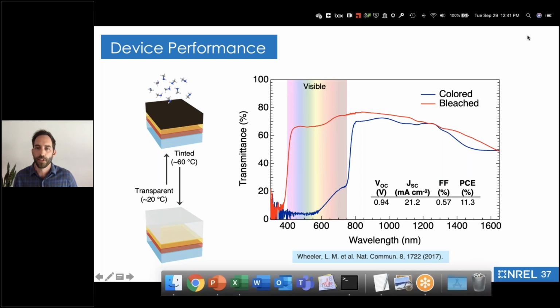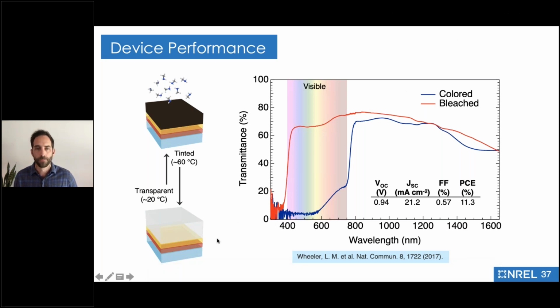And so this is actually really exciting. This is how I got into building science. If you look at this plot on the right side, this is transmittance of the full device stack as a function of wavelength. And we highlight here the visible transmittance, which you can modulate between about 3% visible transmittance in the dark state, where we're absorbing a lot of light. In that 3% state, we convert electricity at about 11% power conversion efficiency. In the light state, we're all the way up to about 65% visible transmittance. So these are pretty dramatic swings in the visible transmittance as well.